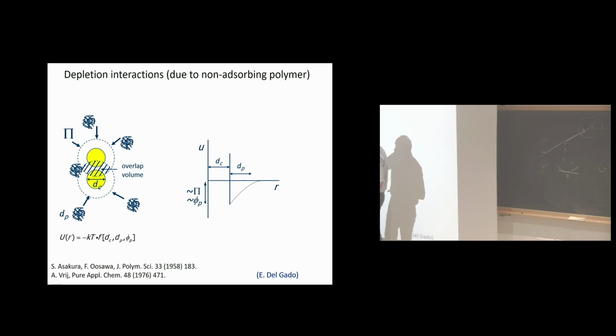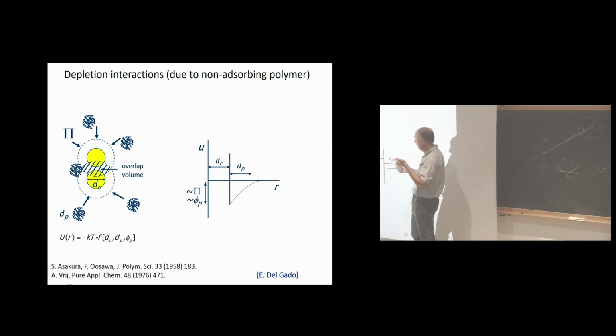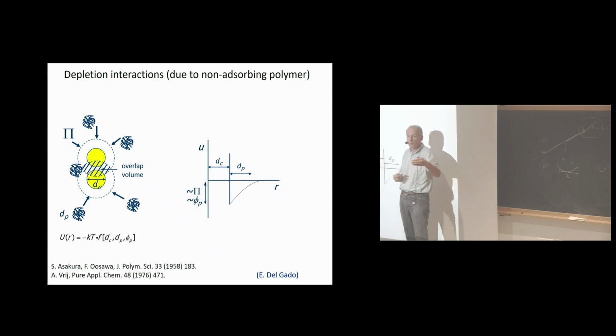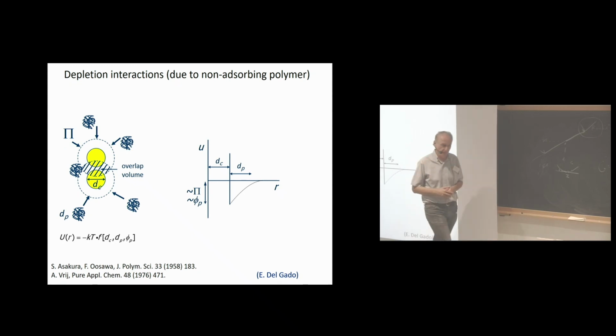And so then, by definition, this creates an osmotic force on the two yellow particles. And Asakura and Oosawa were the first to describe this and came up with the depletion attraction potential, which this one here is hard repulsion, but before this you have this attraction. And so there are three parameters. Obviously, the hard part depends on the size of your hard sphere. You have a range of this attraction that depends on the size of the polymer, and the strength of the attraction that depends on how many polymers you add, right, on the concentration.